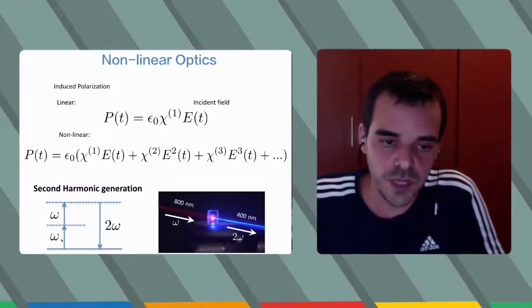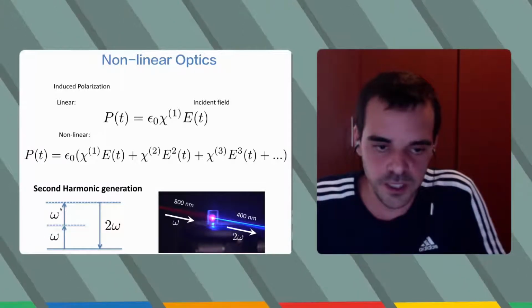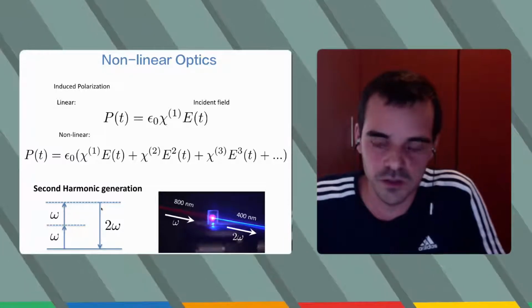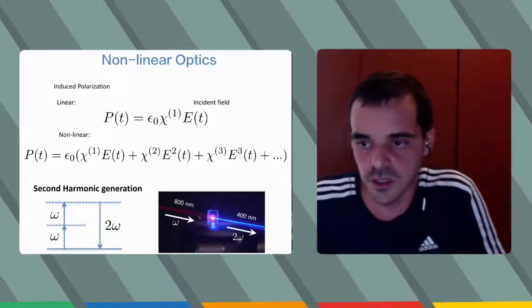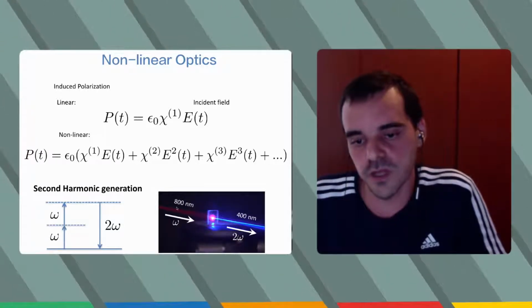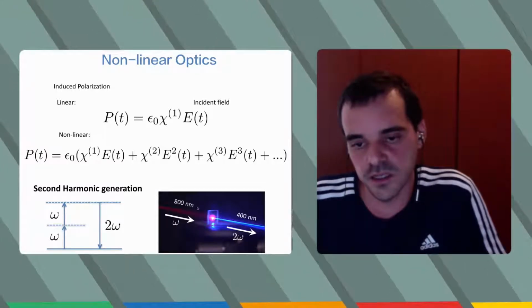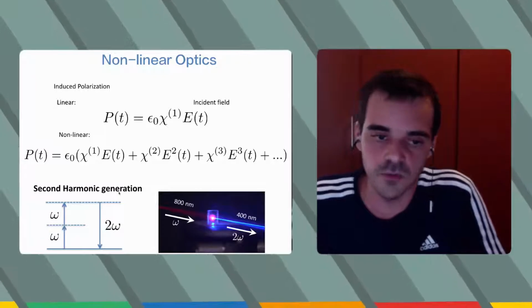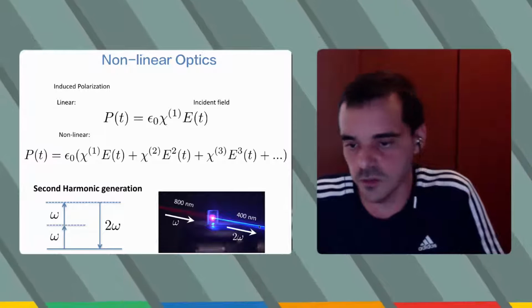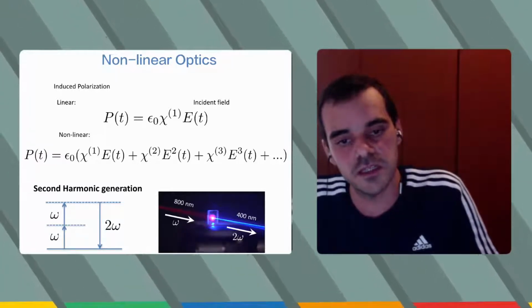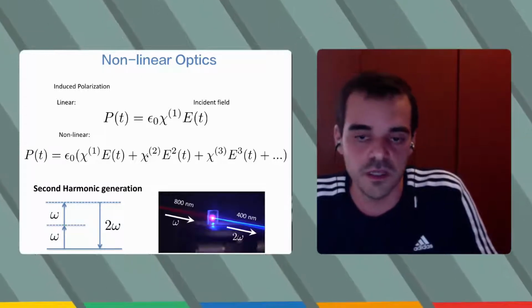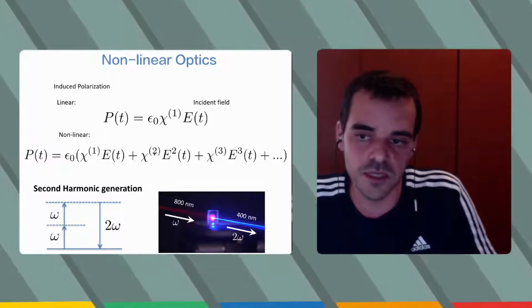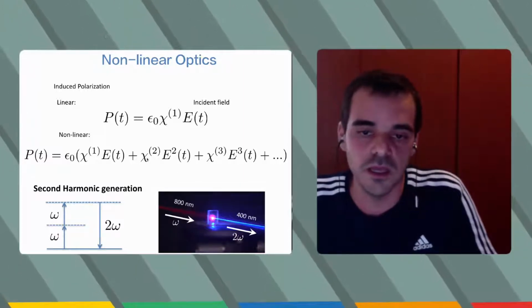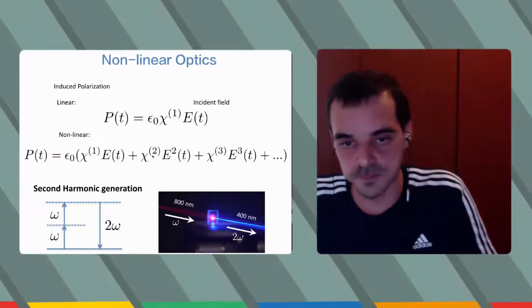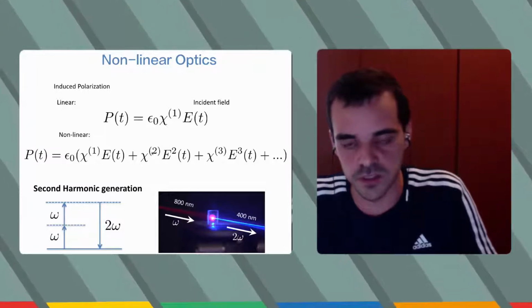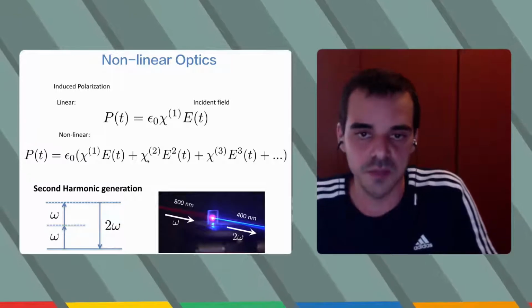In this case, we have the interaction of two photons with energy omega, and the material converts these two photons into only one photon, but with twice the energy. For example, if we excite a nonlinear crystal with an infrared laser at 800 nanometers, then with the second harmonic we will see light coming out at 400 nanometers. This is very interesting because this Chi2 is in fact a tensor. It depends on the symmetry of the crystal. If the crystal has an inversion symmetry, this Chi2 is 0. Also, how the polarization of the electric field